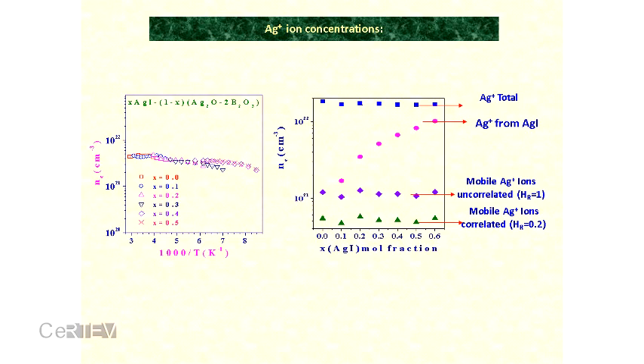And here we have seen the total charge carrier, the charge carrier coming from silver iodide and silver oxide. And here is the charge carrier coming from only silver iodide. In some electrolyte models, it is assumed that the charge carrier is coming from this. So according to our calculation, we have seen that neither the strong electrolyte model nor the weak electrolyte model is satisfied for these glass systems.